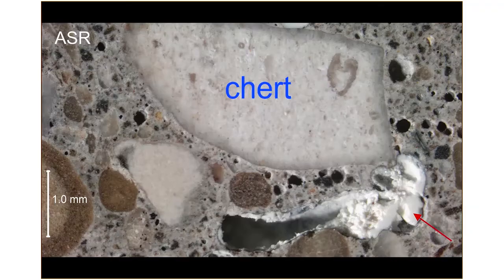There is some alkali silica reaction. Alkali silica reaction is a reaction between a susceptible aggregate that contains disordered quartz. In this case, it's chert. The high alkalis in the paste, the hydroxyl ions, and the alkalis such as sodium, which the whole system is flooded with. There's also potassium and a few other alkalis, and these attack disordered quartz and produce a gel. The gel is hygroscopic, moisture can get to it, it's expansive, and you can produce cracking.